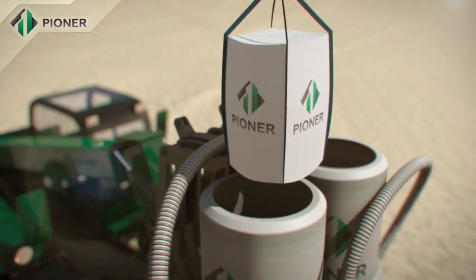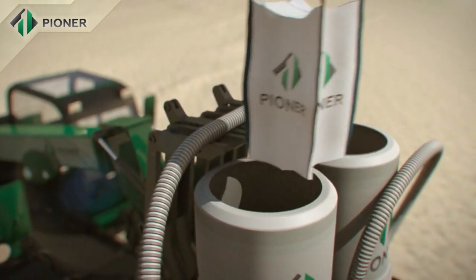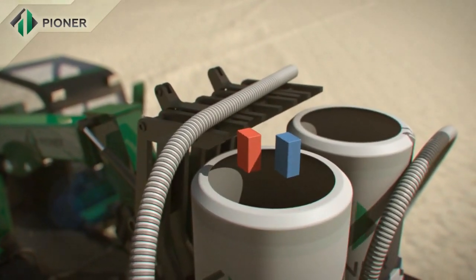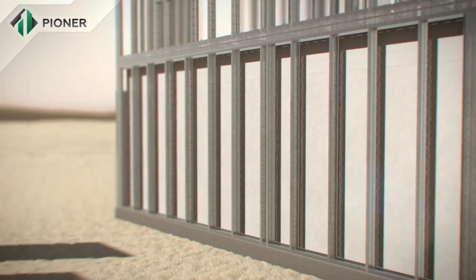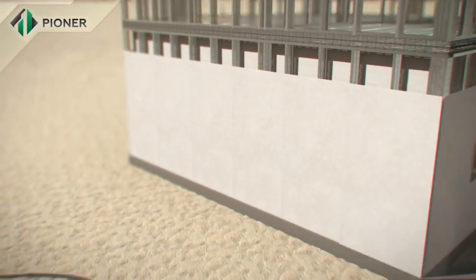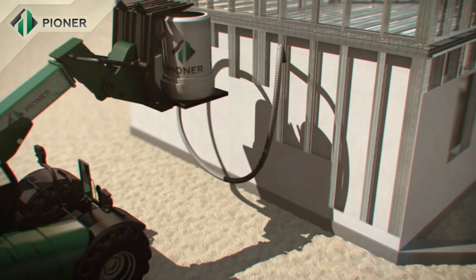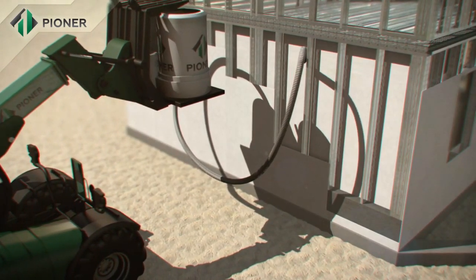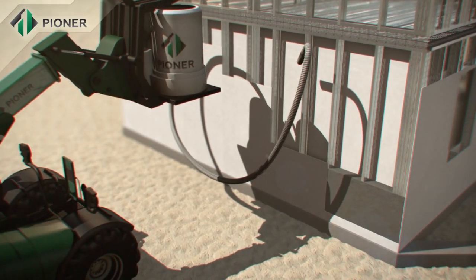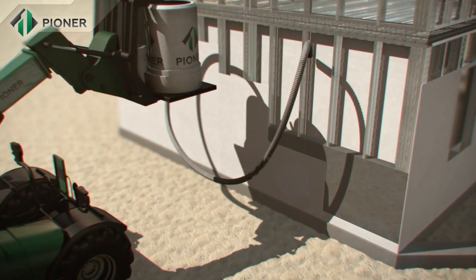Dry mixture of Pioneer compound is mixed with water in a special hydraulic mixer that does not require connection to an electric supply. It is then poured between the installed panels, completely filling the space inside. Within 40 minutes, the mix increases in volume from 2- to 3-fold and turns into a homogenous monolithic structure.